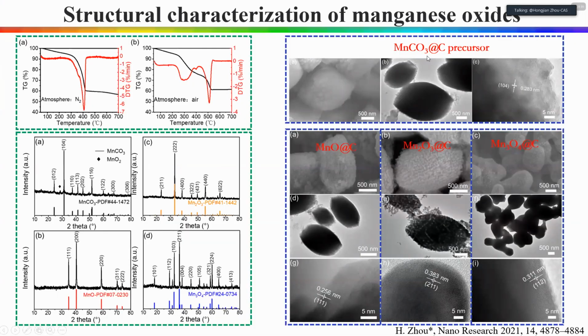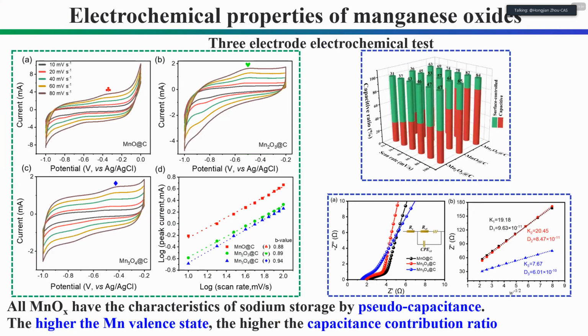So this is our synthesis of the material. We used different characterization technologies to characterize our material. By using TEM and SEM images, we can see that all three types of manganese oxide have almost similar morphology, in spherical shape. And this is the electrode property of manganese oxide. We can find that all manganese oxides have the characteristic of sodium storage by pseudocapacitance, and also the higher the manganese valence state, the higher the capacitance contribution ratio.